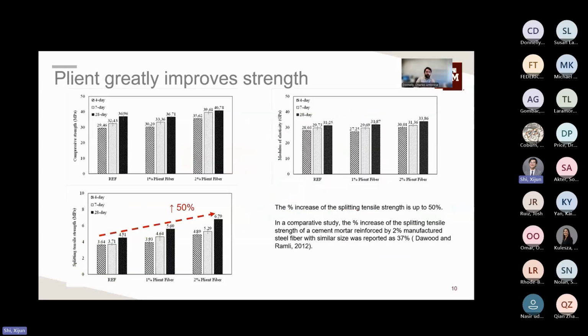In addition, there's been a number of tests done to evaluate the effect of Plient on different strength parameters, namely compressive strength, shown in the top left, modulus of elasticity or stiffness on the top right, and then the splitting tensile strength shown on the bottom. The key takeaway from these results is that using Plient in different dosages can slightly increase your compressive strength and has minimal effect on your modulus of elasticity, but critically, increasing your Plient dosage has a significant effect on the splitting tensile strength. That plot on the bottom shows that an increase from no Plient fibers in the reference concrete to 1 or 2% Plient fibers can show an increase of splitting tensile strength, resulting in as high as a 50% improvement of your splitting tensile strength.